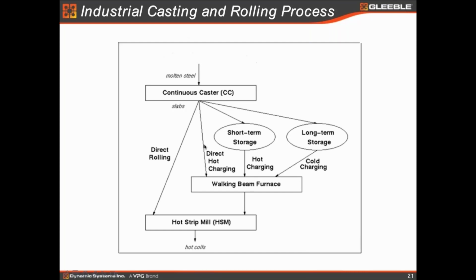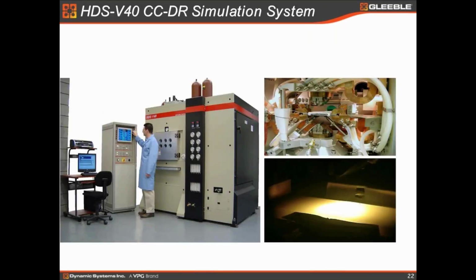Then we got direct hot charge, just like the second schematic testing scheme I showed in the previous slide. And now, as we all know, almost everybody is using CCDR to produce all kinds of thicknesses of strips using a hot strip mill, no matter if it's 5 stands or 7 stands, depending on the thickness that you are going to produce. Fortunately, DSI has developed a CCDR simulator. We call it HDS V40. HDS stands for hot deformation system, and V40 is a vertical 40-ton machine. We are using a very large sample, as you can see here. The normal specimen is 10 millimeters thick by 50 millimeters wide and 250 millimeters long, depending on the free span that you want to set.